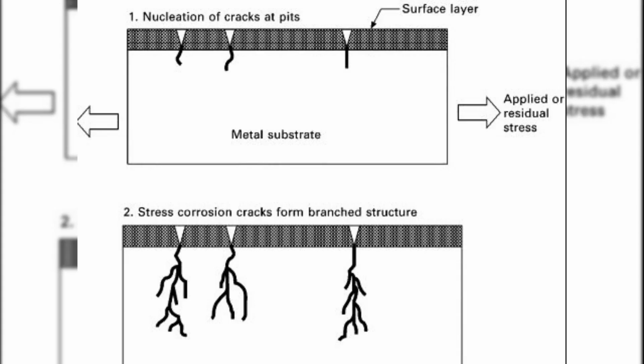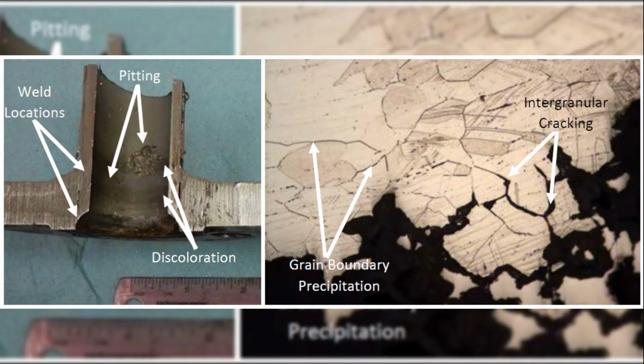One of the most dangerous forms is stress corrosion cracking. Here, corrosion interacts with mechanical stress. Even relatively low tensile stress, combined with a specific corrosive environment, can initiate microscopic cracks. These cracks propagate rapidly, often without visible plastic deformation. Components can fracture suddenly and catastrophically, with no clear warning signs.